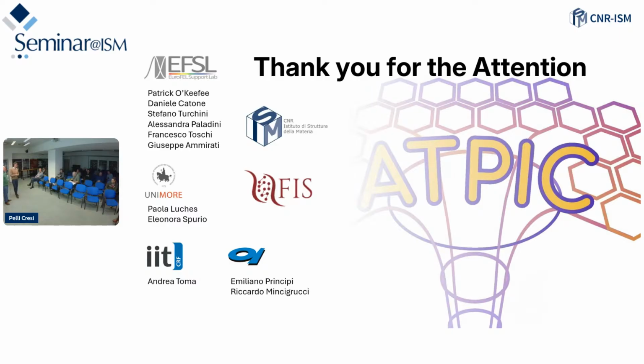Thanks, Stefano. I saw the large polarons have binding energies of like 10 meV. So I guess you're only going to see this in cryogenic states, so you have to cool it down. So for real world effects, it's not going to be a major point, I imagine, the large polarons. Yeah, exactly. The small polarons, on the other hand, have much bigger binding energies. You're saying that it limits the recombination. So when you form the small polaron, you create a reservoir of states for photocatalysis, so that it lengthens the lifetime of the carrier involved.